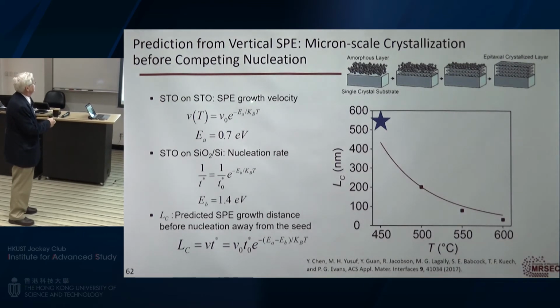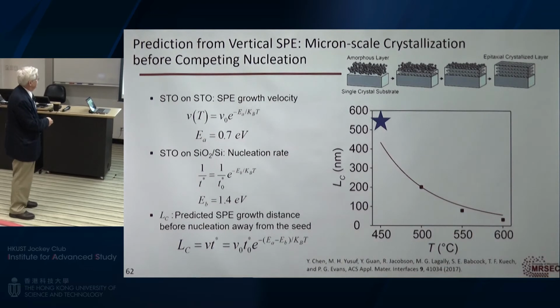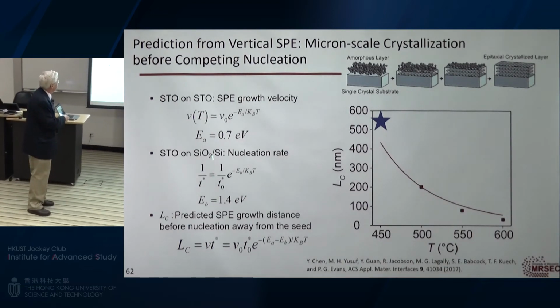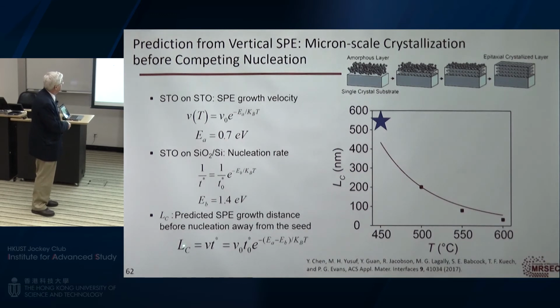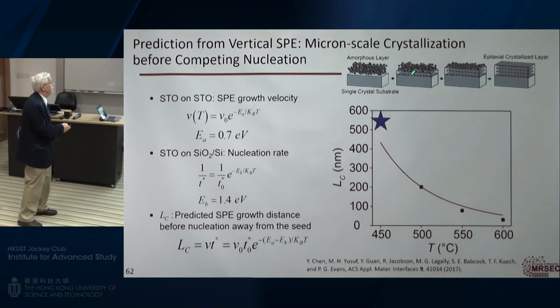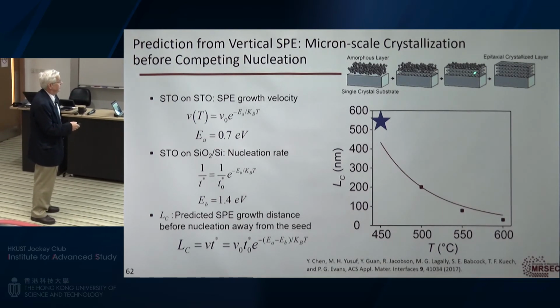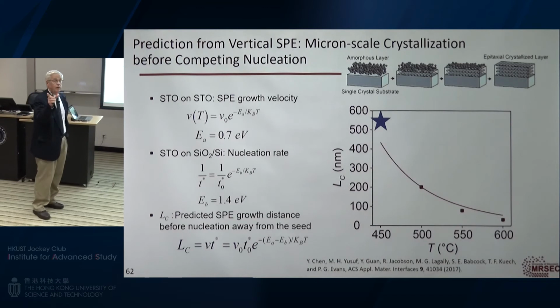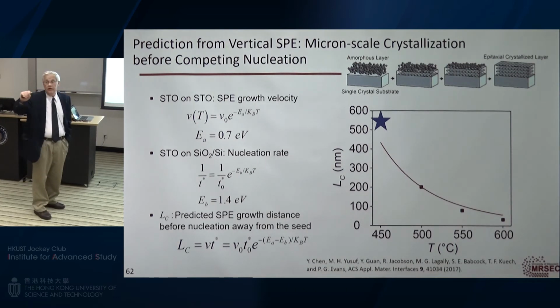So this is the vertical growth rate and the nucleation rate. And so what this says is that from the data that I showed you, I can use this to say how far I can regrow the material from an epitaxial seed, or form this single crystal material, before it'll start forming other homogeneous crystallization and other little crystallites. And you find that you can actually grow, depending on the temperature, several microns of material. So the idea is that you have an amorphous layer and you start it to recrystallize or reorder through the amorphous film, and that'll reorder and recrystallize that whole amorphous layer.